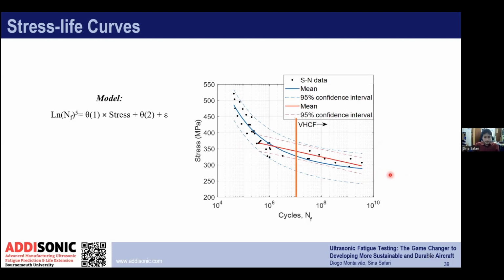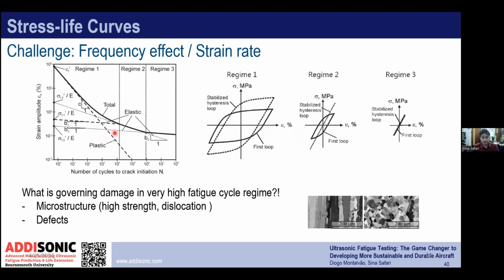Okay. So if we move on to the next slide, this again shows different fitting methods for different models we can use. In the very high cycle fatigue regime, I use the linear model, or I put the whole data together and use the nonlinear model. And there is a reason for this, because some literature proposes that if we continue the regime we are observing in the low cycle to the high cycle and very high cycle, we will get a good estimation of the S-N curve.